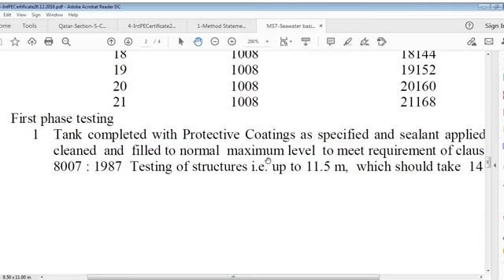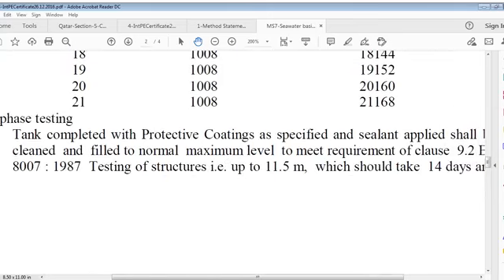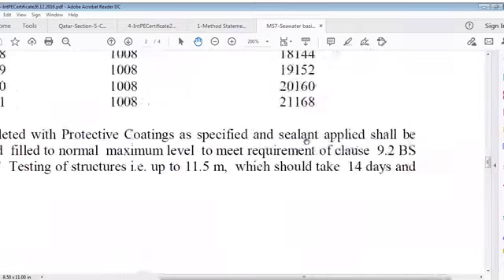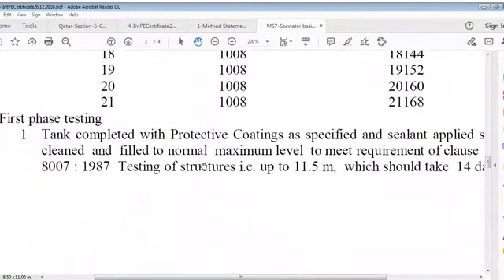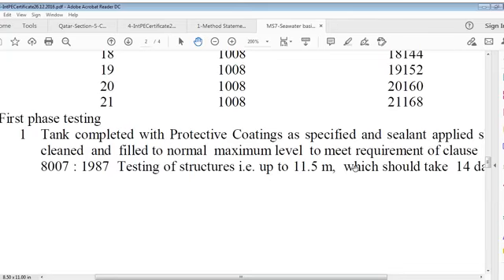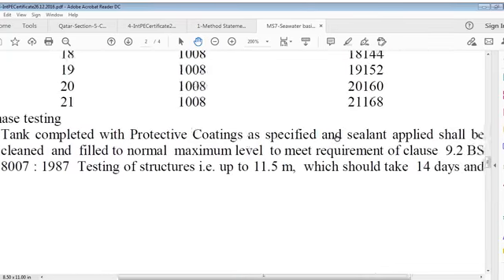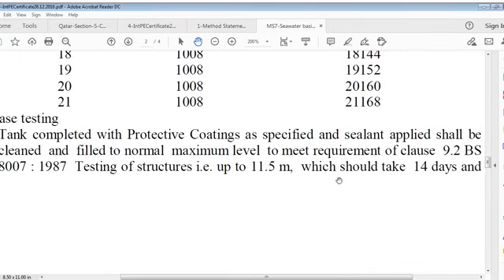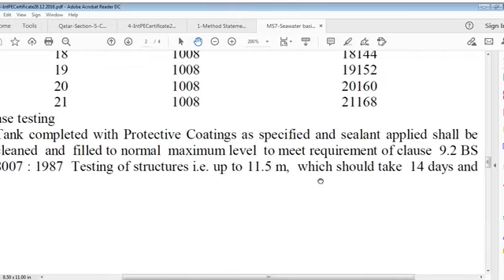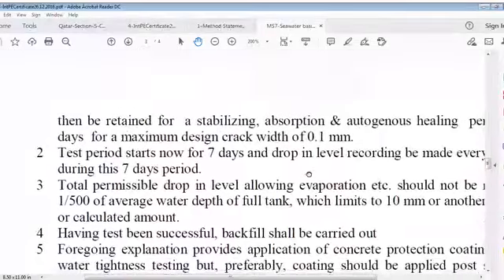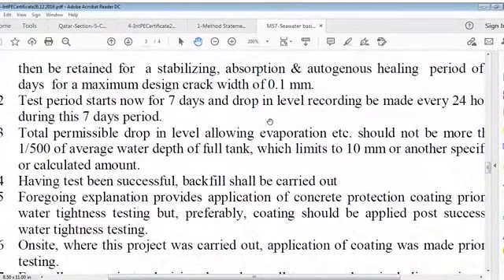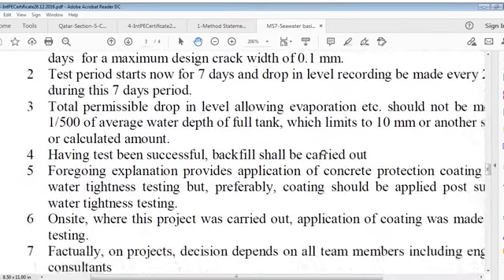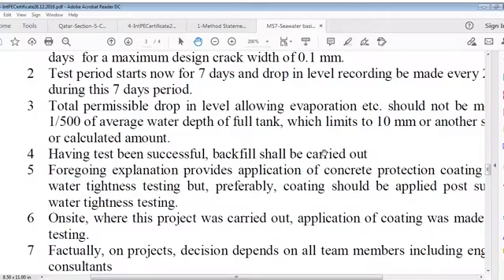Well, it depends. BS 8007 doesn't accept that, but something is wrong with the specific. Well, we are talking of procedure. And sealant applied shall be cleaned and filled to normal maximum level to meet requirements of clause 9.2 of BS 8007:1987. Testing of structures, that is up to 11.5 meter, it should take 14 days, and then be retained for a stabilization, absorption and autogenous healing period of 7 days for maximum design crack width of 0.1 mm.